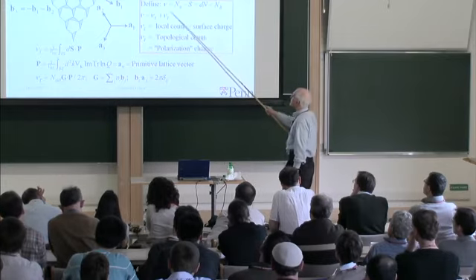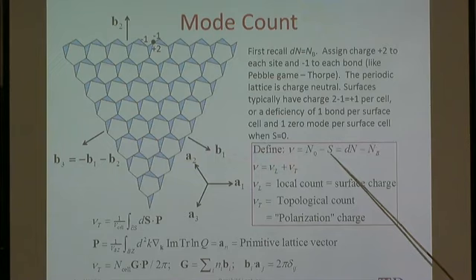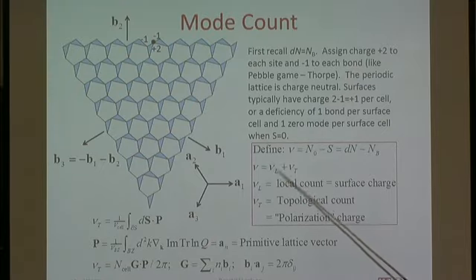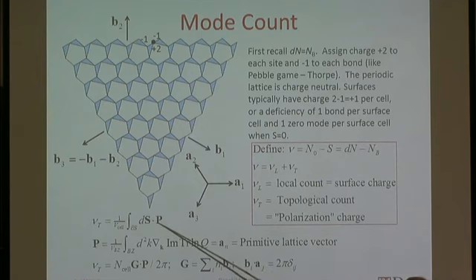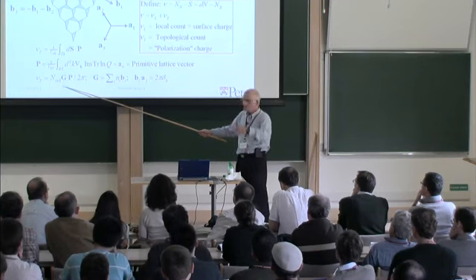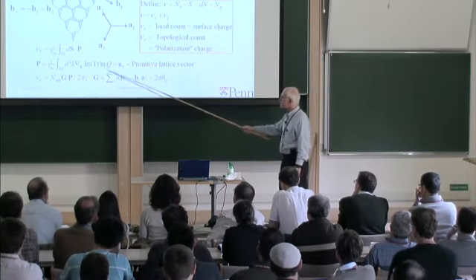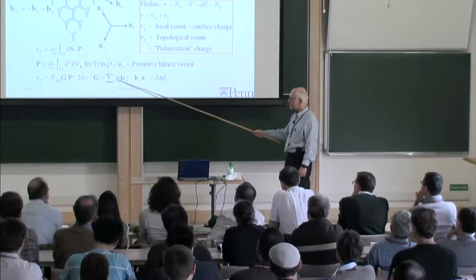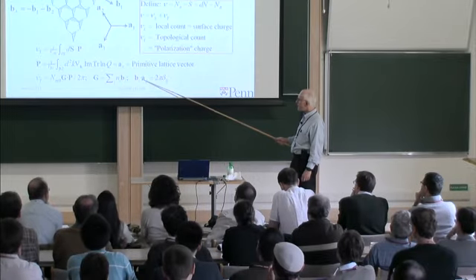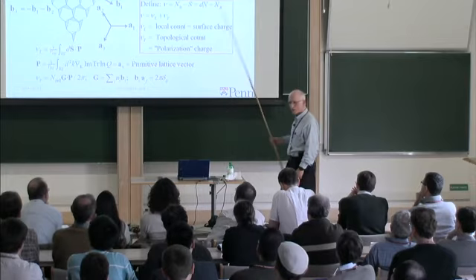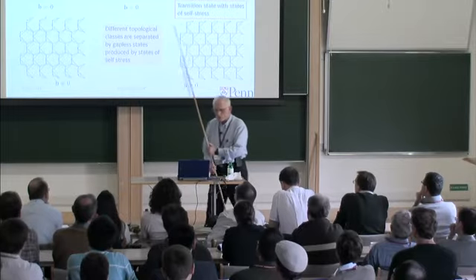So we can then define this thing nu, which is the number of zero modes minus the number of states of self-stress, which is d_n minus n_b. And we can break this up on the surface into a local part and a topological part. This is the local count. This is the topological count. And the total value of this is ds.p, so it depends on s and the direction of p, so that the topological charge is the number of cells, the reciprocal lattice vector that's normal to the surface divided by 2 pi. And G, of course, is exactly the reciprocal lattice vector. It's the sum over n's of the reciprocal lattice generators. And a is the direct lattice things, where b_i.b_j is 2 pi over n_ij. So let's just see how this works out.